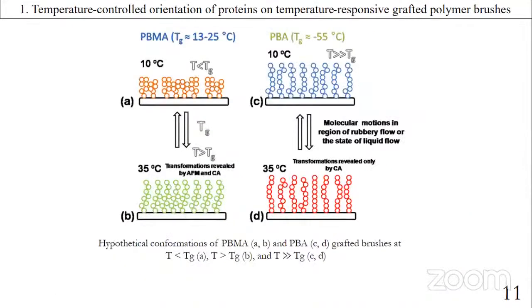Based on our experimental data, we propose a hypothetical scheme for the temperature sensitivity of the PBMA and PBA grafted brush coatings at temperature close to the physiological limit. At temperature less than glass transition temperature, PBMA grafted brush coatings are in a glassy state with polymer chains. In contrast to the glassy state, at temperature more than glass transition temperature, the properties of the PBMA grafted brush coatings are essentially different. The studied temperature interval for PBA grafted brush coatings is far from glass transition temperature, and we can state that the PBA coatings are in a rubbery state.